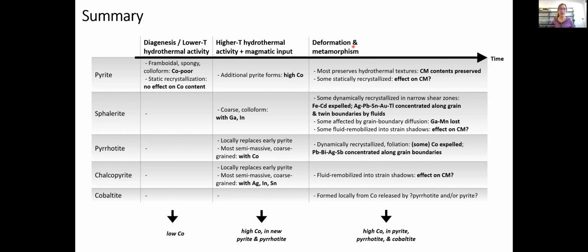And then we go and deform and metamorphose everything. Well, we still have a lot of cobalt in the system. It didn't go anywhere. It's still mostly sitting in the pyrite, which kind of just shrugged off the deformation. But some of the cobalt that was in the pyrrhotite might have been remobilized, extracted from that pyrrhotite when it recrystallized, and gone on to form cobaltite. Still need to confirm this, but it's a cool model.